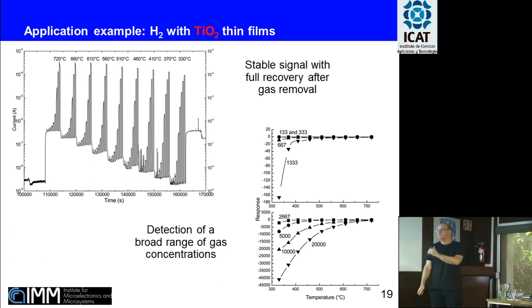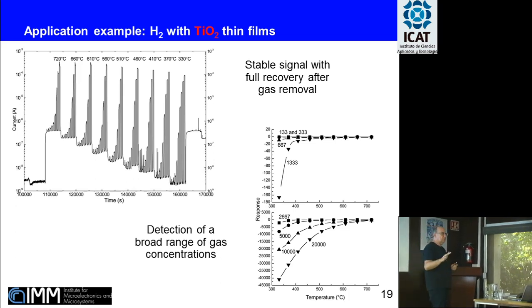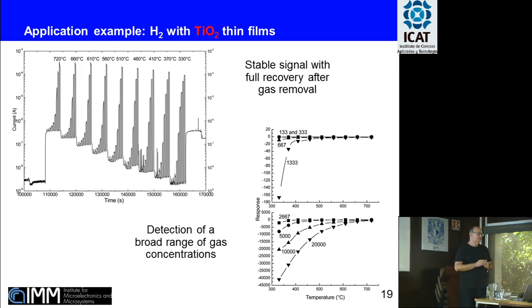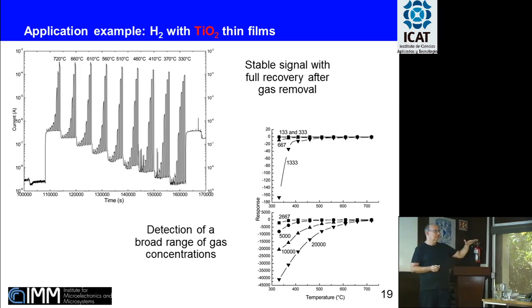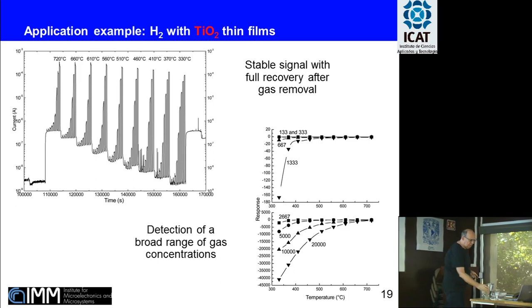The problem was that still the responses that we were obtaining were not so high. This is because the preparation of thin film is a limitation to the porosity of the material that you are using. For this kind of application, gas sensor, it is important to have a porous material. If you have a thin film which is then deposited onto a substrate, most probably you will get a very, very low porosity, because the contact area between the device and the gas is just limited to the upper face of the film. You don't have any other contact.